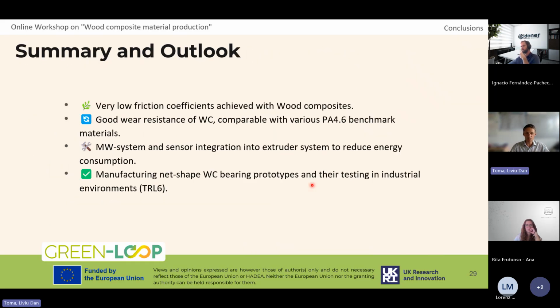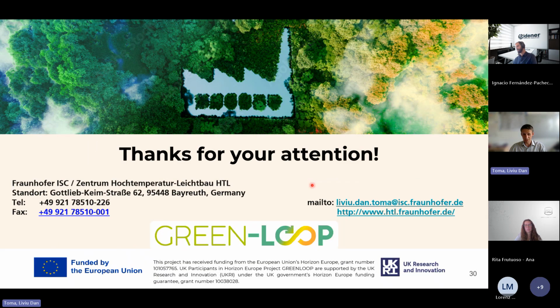So just a short summary and outlook. Very low friction coefficients were achieved with the wood composites. We had good wear resistance for this, and we integrated the microwave system and sensors into the extruder system to reduce the energy consumption, and we were able to produce near net shape wood composite bearing prototypes, which are currently on the way to being tested in industrial environments. And for this, thank you for your attention.